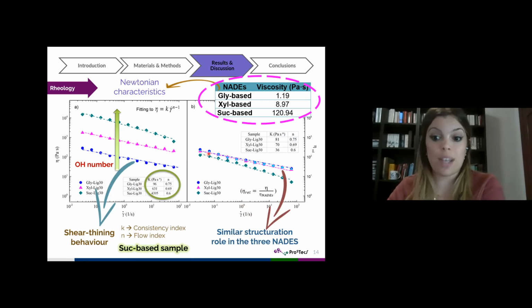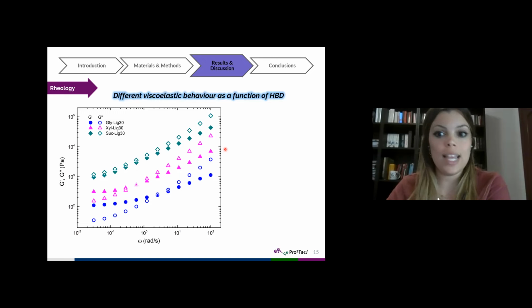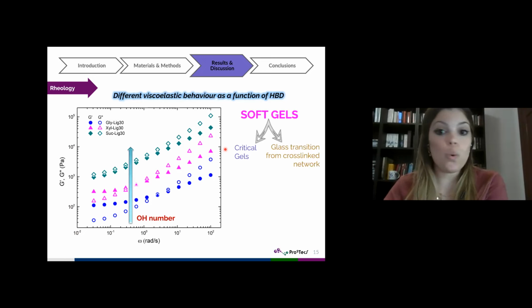Well, finally, the formulations were evaluated from a viscoelastic point of view, obtaining different rheological behavior depending on the type of hydrogen bond donor compounds used in the synthesis process. The values of both the storage and the loss moduli increase with the number of hydroxyl groups comprising the hydrogen bond donor component, showing both viscoelastic moduli similar values and characteristics of soft gels, which resemble either a viscoelastic response close to critical gels or a glass transition from a cross-linked network.